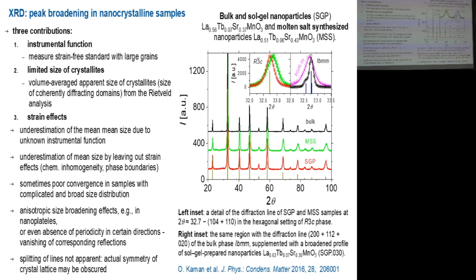In 2 samples, in the nanoparticles prepared by molten salt synthesis and in sol-gel nanoparticles, of these compositions, you can see like a broad diffraction peak. Actually, there are 2 very close diffraction lines here, 104, 110, but they are very, very close to each other. So you cannot distinguish them, not even in the bulk sample. But the problem is that the line broadening is really large, and you can see just a broad peak.